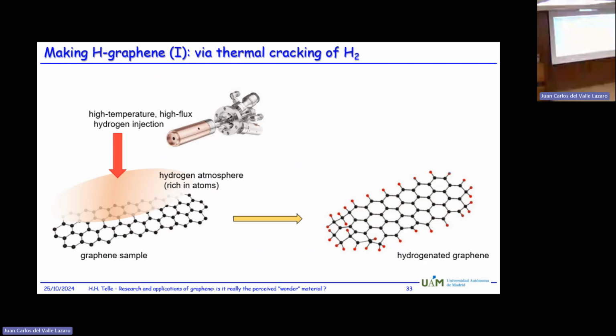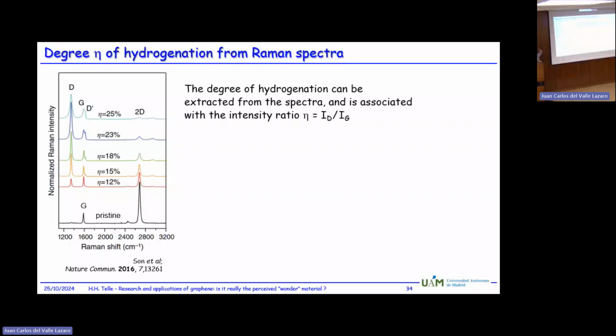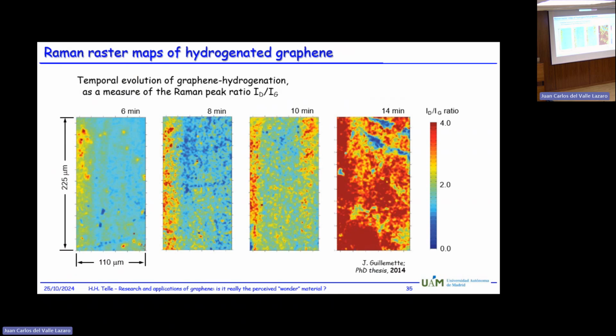So now you can probe your sample once it has been exposed to hydrogen. I don't know whether this is clear enough to see from the very back, but you can see that from the pristine situation where you have these two dominant peaks, the system completely changes: this peak disappears and an additional peak appears. So from the ratio of these two peaks, you can determine how much hydrogen has been absorbed on the graphene. And you can then also make maps of this and distinguish how well and equally it is distributed.